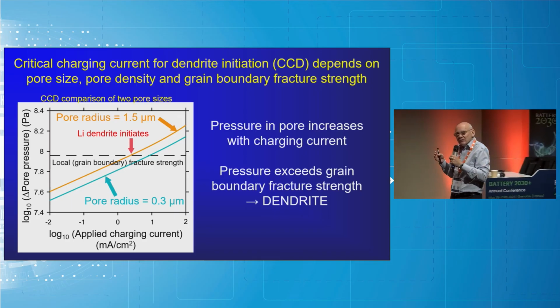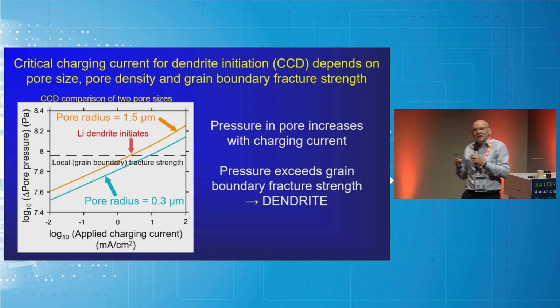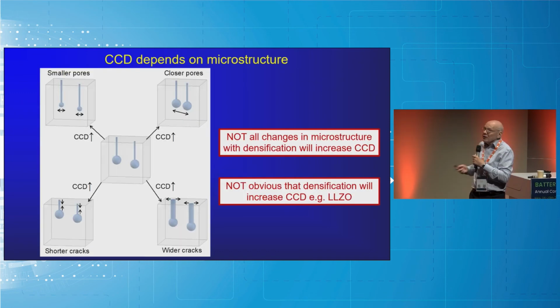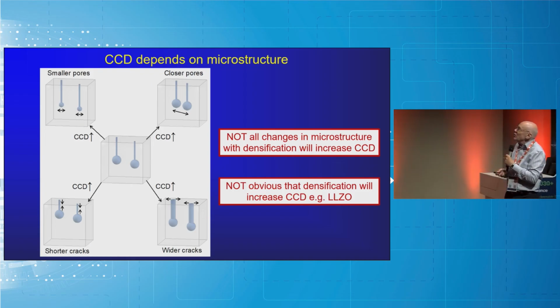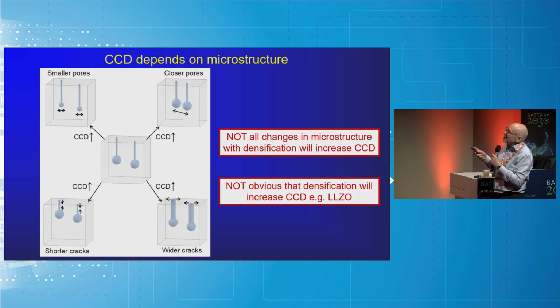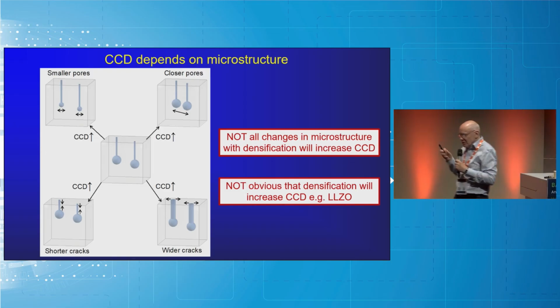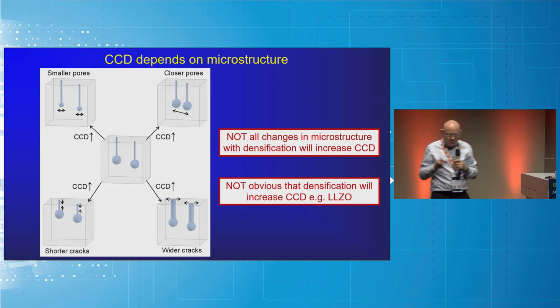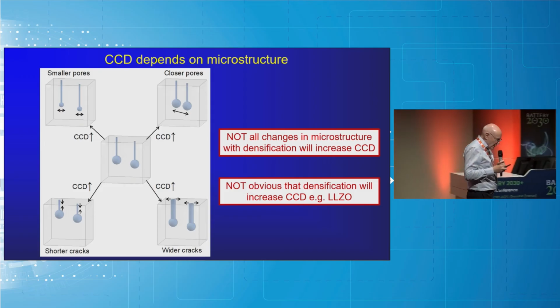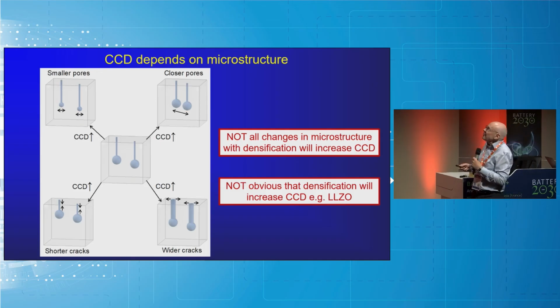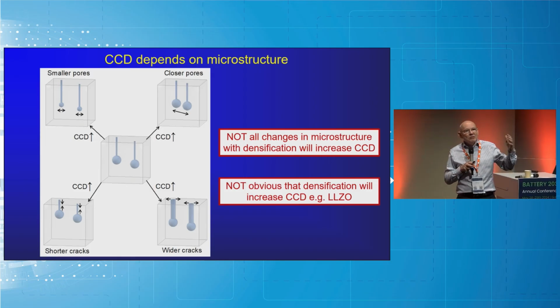But it's the whole microstructure of the ceramic electrolyte that you really need to take into account. I won't have time to go through all of these points, but I just want to make one or two comments because I know we want to get back on track a little bit here. It's the whole microstructure. In other words, it's not just the pore size and its distribution, but also the crack lengths and the widths. And unfortunately, when you densify a ceramic, not all of those things are going in the right direction to increase the critical current for dendrites. Some make things better, some make things worse.